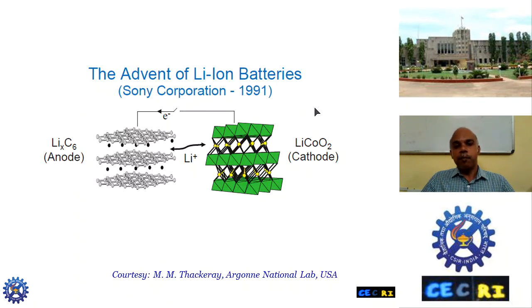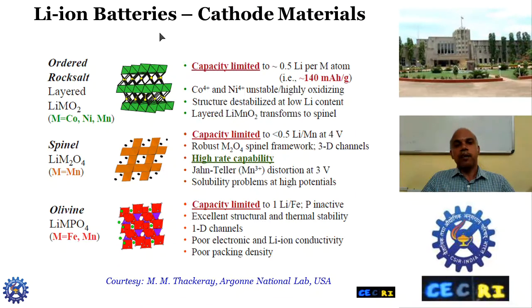So the advent of lithium-ion batteries: this is how the Sony Corporation made it, using lithium cobalt oxide as cathode, from which lithium can be removed to go to the graphite anode. This can go back to the cathode during the discharge process. A variety of cathode materials have evolved. For example, in the ordered rock salt structures, LiMO2, the problem is that only 0.5 lithium can be removed per metal atom, whereas in the spinels you can get higher energy, 4 volts. This structure is robust, so it can hold up. But again, there are issues with the Jahn-Teller distortion of manganese 3 plus at 3 volts, and solubility problems at high potential.